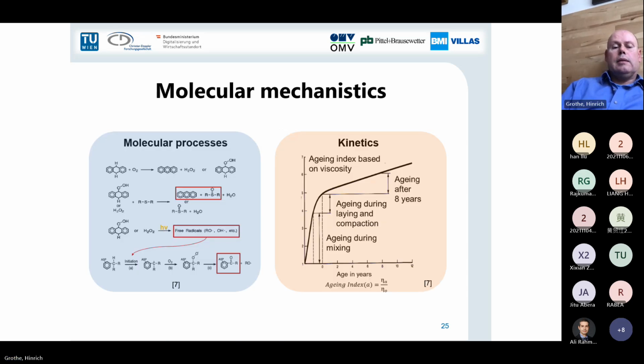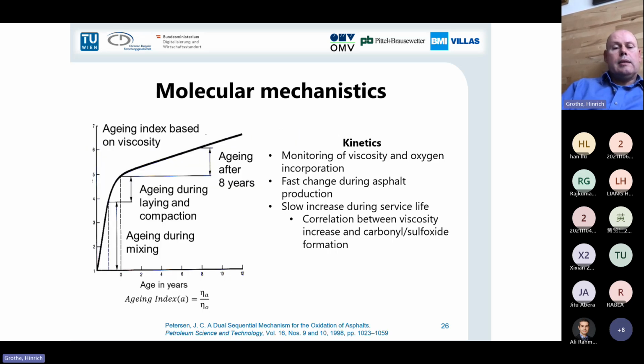And as I said, the temperature is different at the beginning, but then the temperature is restricted up to about 80 degrees. So this graph here is viscosity against time. But what is more important for us is to see how the oxygen is incorporated into that material, how the polarity is changing, how the material is chemically altered. And for that, infrared spectroscopy, for example, will give a much more interesting result.